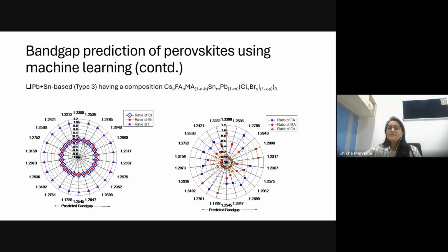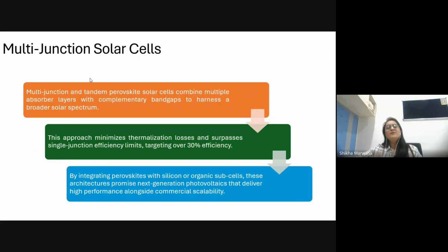So I'll go for this. Here we see that when we were checking this tin based material, the contribution by chlorine was very small, so it was mostly from bromine and iodine. We were able to make a few predictions based on halide ratios, and for cations also, so we got some good results. And if I talk in terms of multi-junction technology, the same material compositions can also be used to increase the efficiency of our material. We can also go for the individual material compositions that I have mentioned. But if I use multi-junction technology, it can surpass the limit of only 30%, and we can go beyond this.